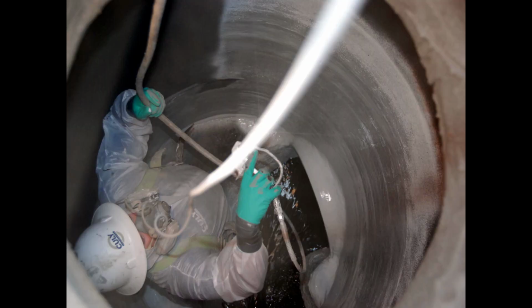And that's what they're doing in this next slide. They've just finished the mortar in this manhole maybe 20 or 30 minutes before this picture's taken. They enter the manhole and they spray a 100% solids epoxy product. 100% solids means it doesn't contain any solvents, and it has essentially zero shrinkage, so wet film thickness equals dry film thickness. And they're going to spray this corrosion barrier on the inside of this manhole at 125 mils. We do spray it thicker than that in some cases, but if you have the restoration mortar underlayment, there's really not any need to go much above 125 mils.